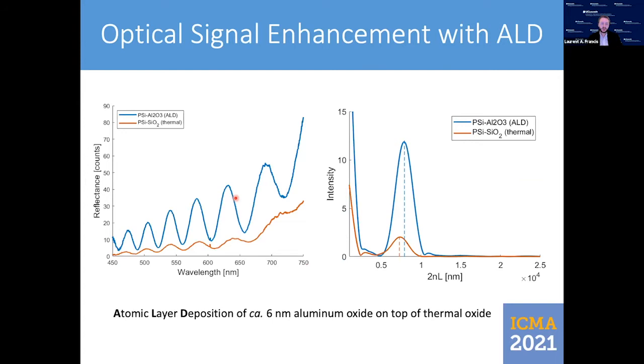So we were wondering if we could not make it better, and therefore we have added by atomic layer deposition a thin layer of aluminum oxide in the pore, here about 6 nanometers thick, which is going to reduce the dimension of the pore. But we can see clearly that we have a stronger signal from an optical point of view, which is also seen here in the Fourier transform of our signal. When we have this ALD layer, we have a 5 to 6 times higher signal back from the biosensor substrate.